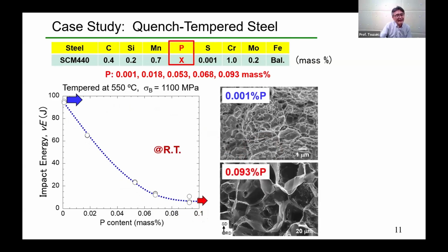At 0.093% P, almost complete intergranular fracture is observed. Here, I should say that even after high temperature tempering, embrittlement due to P is still pronounced.